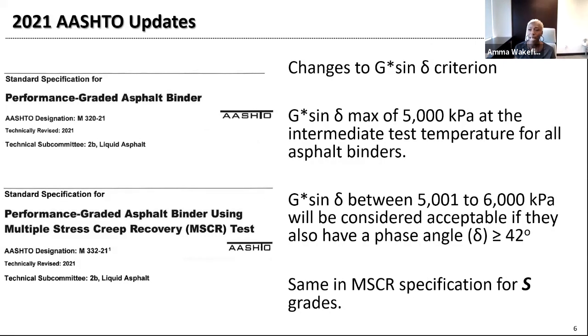And so through research, we've determined that binders that have a G star sine delta above 5,000 and up to 6,000 can still be considered acceptable as long as you look at the phase angle. This is information that is pertinent to testing labs to ensure that they are looking at the specification and not rejecting binders based on that parameter because it's updated, but also to let agencies know that suppliers are aware of these changes in the AASHTO specification, and they are going to be adhering to those going forward. So this is an awareness for agencies to know that the AASHTO specification has changed. It's a small change, but it's impactful if you're not making sure that you do look at the phase angle if the G star sine delta falls within 5,001 to 6,000 kPa.